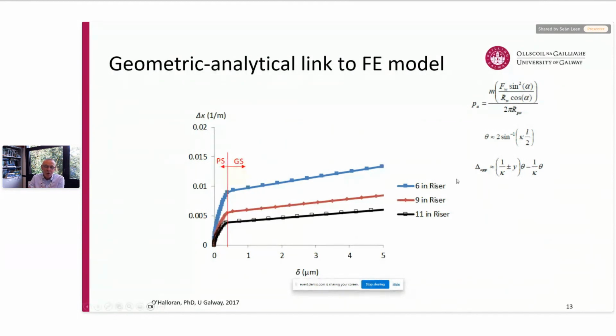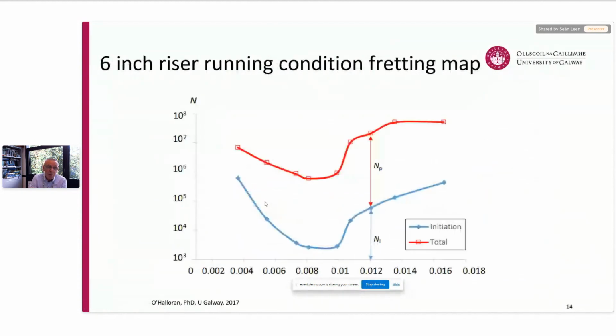And we can do that for a range of different geometries of risers. We've looked at 6, 9, and 11-inch risers in this case, and we can identify the gross slip and partial slip regimes for those. That allows us to generate what are called running condition fretting maps, or RCFMs, which allow us to look at how the life of the riser depends on the curvature, or the curvature range, the dynamic curvature coming from the global model.